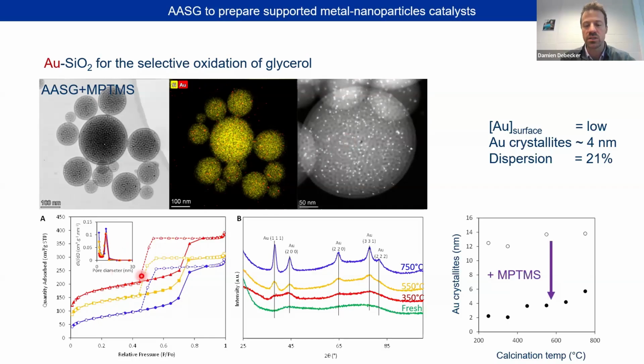You keep the porosity, and you see here that the fresh catalyst is totally amorphous, and it's only when you calcine at 550 or 750 that you start to see the gold nanoparticles. This is also another way to illustrate it. The effect of the mercapto group is that you decrease the size of the calcined nanoparticles.